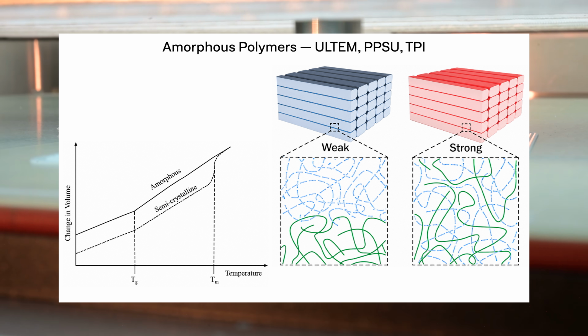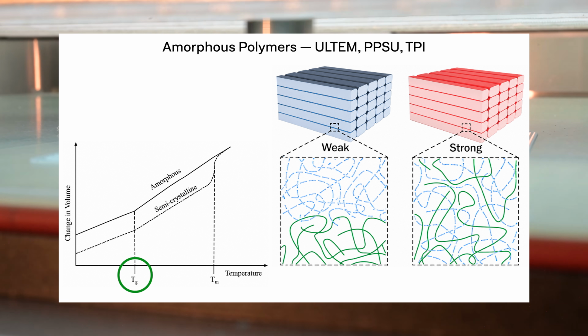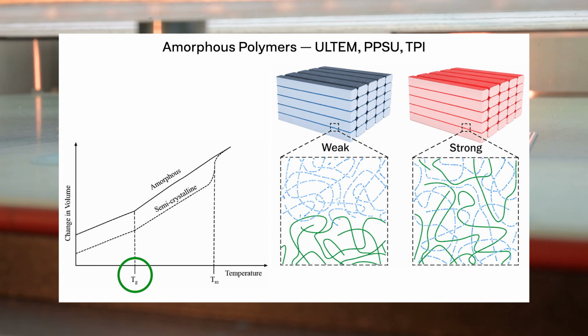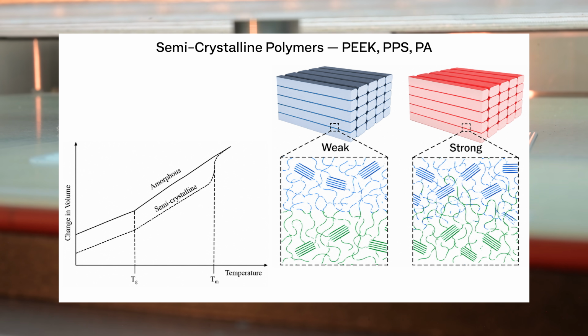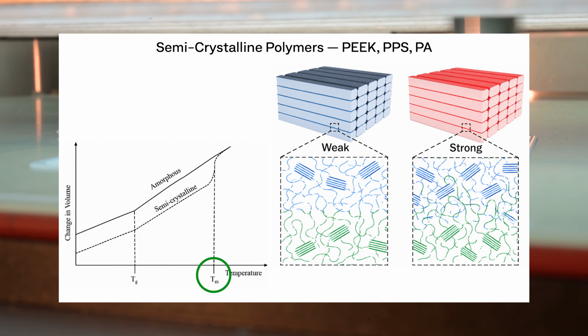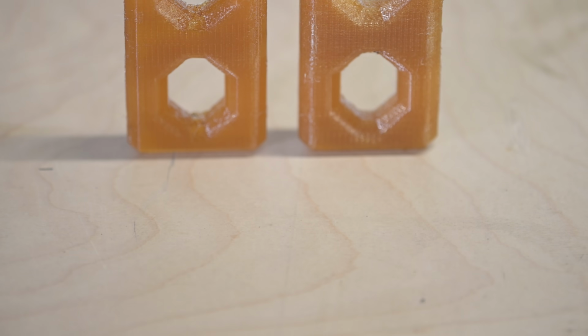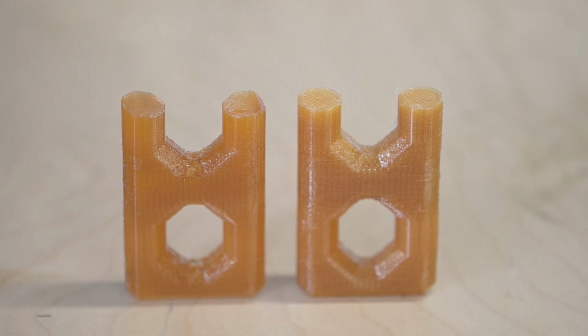The chamber temperature needed to preserve that mobility differs by polymer. For amorphous materials like ULTEM, the welding window centers around the glass transition region. For semicrystalline materials like PEEK, the ideal chamber temperature is generally closer to the material's melting and crystallization range. In either case, a hotter chamber slows cooling and extends the time available for strong interlayer welds to form.